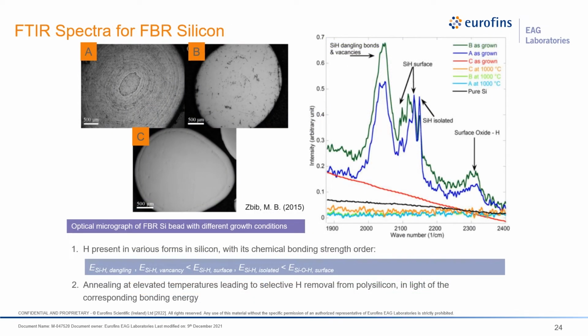One of the research studies investigated different structure in these beads. The Fourier transform infrared spectroscopy clearly shows the difference and confirms the bead A and B have the presence of hydrogen bonded with silicon. As you can see here, grain C doesn't have any feature, and the intensity for that particular grain falls in on this line as well as on this orange line over here.